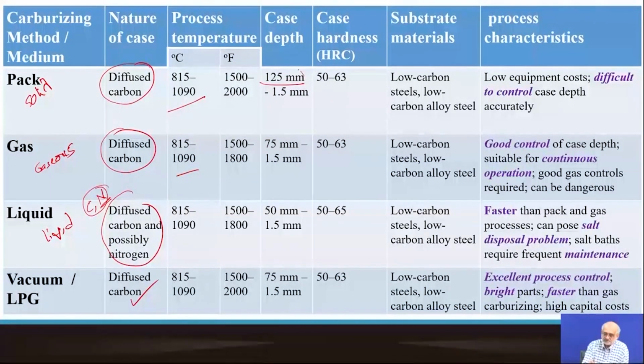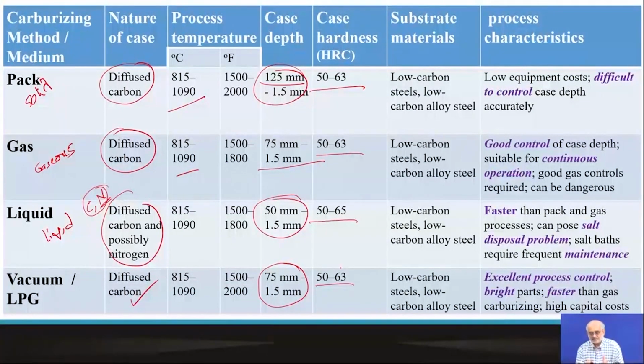Lower in case of gas carburizing, and certainly the lowest in case of cyanide bath or liquid bath carburizing. In vacuum carburizing, you actually can achieve this with a much smaller time period. The case hardness range will be very similar, depending on the time temperature combination, what carbon potential we have used, and so on. The substrates are very similar in all the cases: plain carbon steel, low alloy steels, or even high alloy steels, and so on.